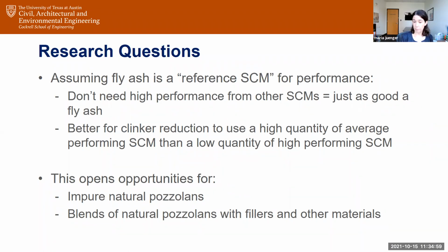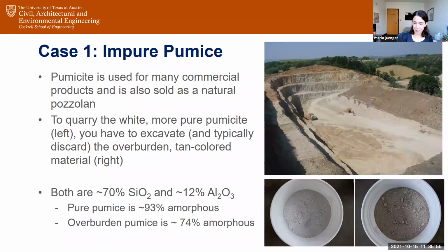If we're assuming that fly ash is a reference SCM, a reference supplementary cementitious material, we don't really need great performance. We need just good enough performance. And actually, to reduce the amount of cement in your system, it's better to use a high amount of mediocre material than a very small amount of really good material. So in terms of balancing and materials design, it makes a lot of sense. This opens up opportunities for using less desirable natural pozzolans or blends of materials to target a performance and cost perspective. So we're designing the system to be average. It's really counterintuitive. You usually want to design something to be optimal. We want to design it so that we can use it cheaply, abundantly, and get okay performance out of it. So the first case study I want to give is what we're calling impure pumice.